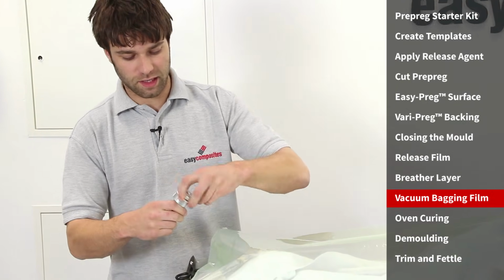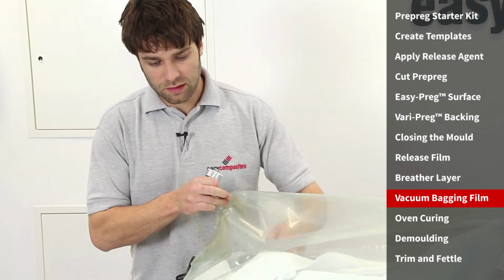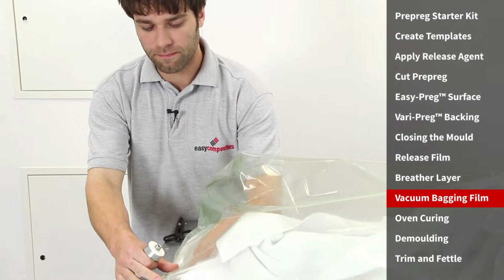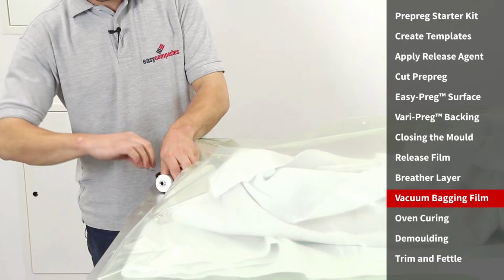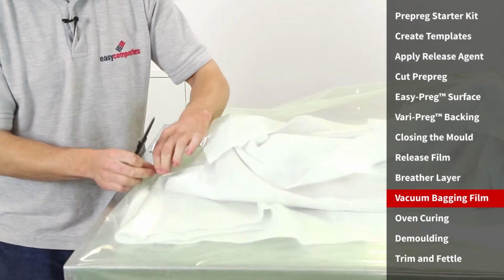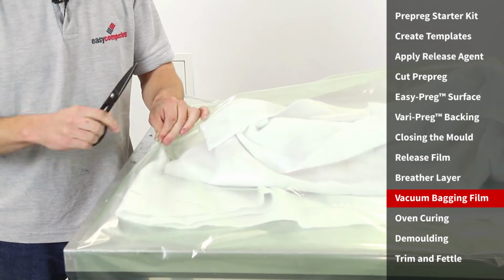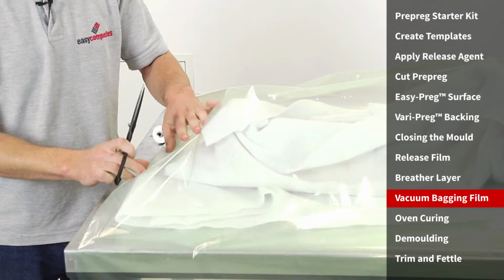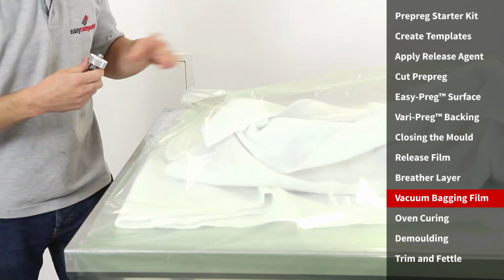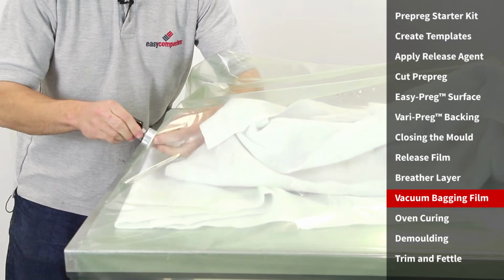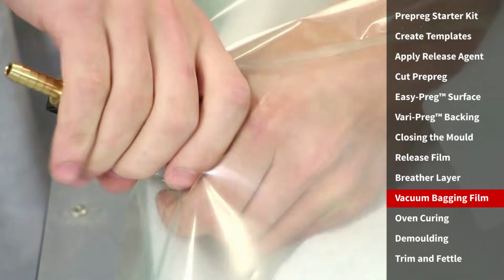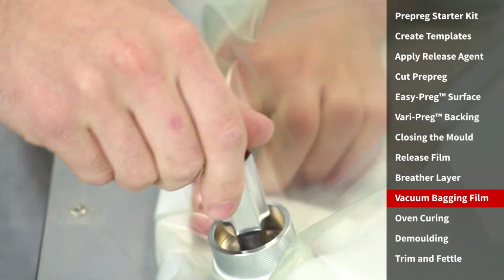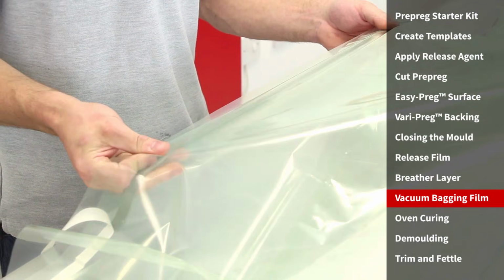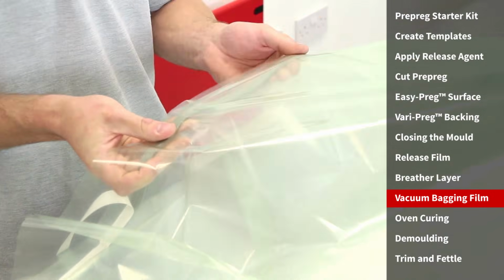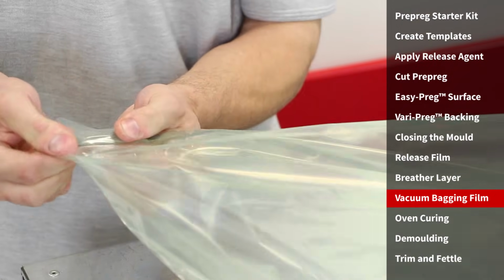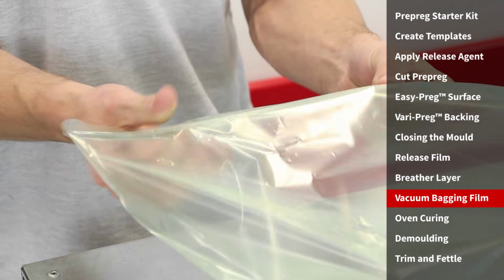Through bag connectors, the next thing, easily forgotten. So we put one insert on the inside there, and then pinch a small amount of the bag, snip it, place that side of the insert through the bag, and then firmly tighten the two together. And now that both the part and the through bag connector are where they should be inside the bag, we can peel off and seal the tape that we positioned earlier.